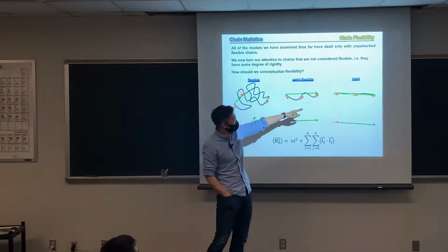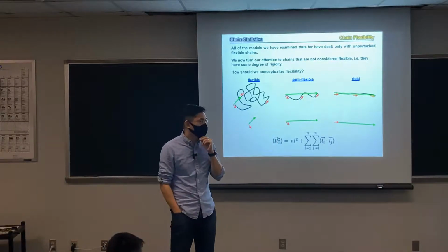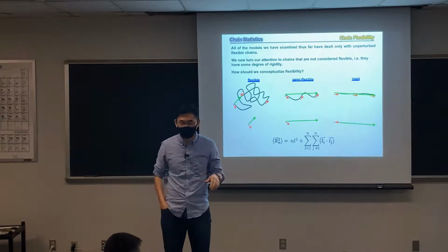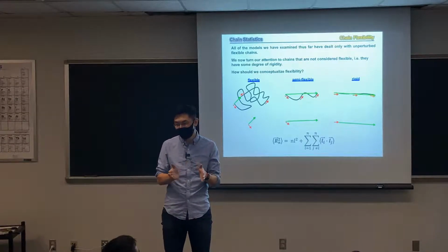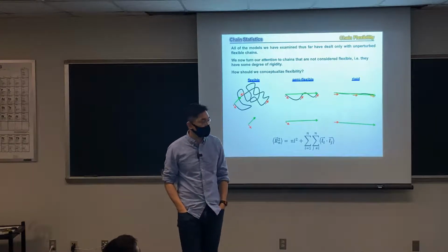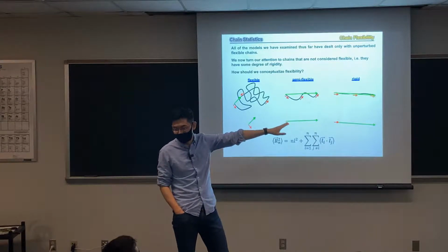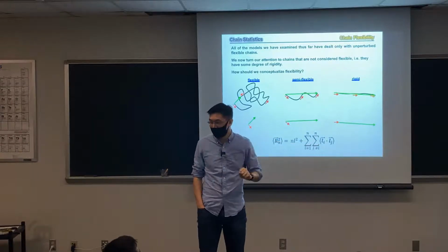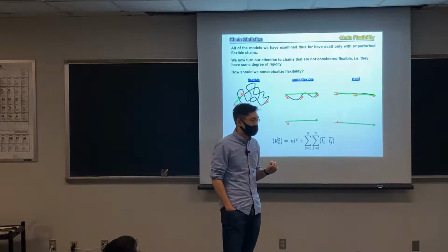So what is a really rigid one? Some of the newer development that my colleague at Texas A&M University is working on is called ladder-type polymer. Not only do you have a double bond, you have fused rings all around the backbone, so you could have a very rigid structure. He hasn't measured the persistence length, but we expect it to be tens of nanometers. The other one that everybody is familiar with is double-stranded DNA. Everybody has DNA in their body.